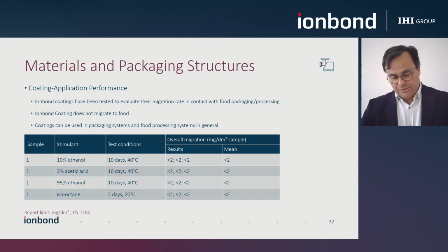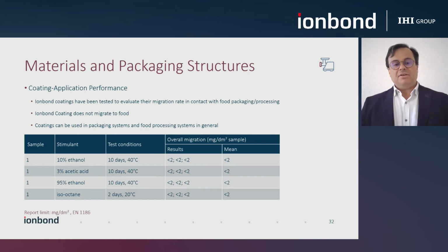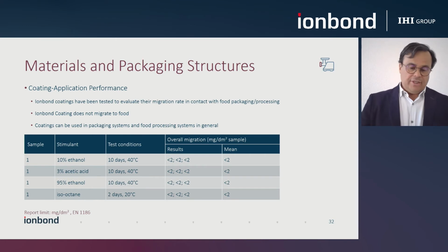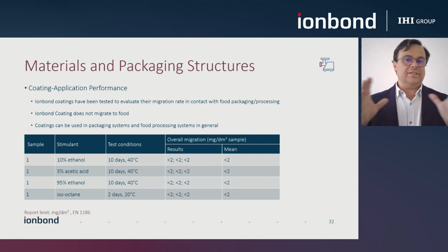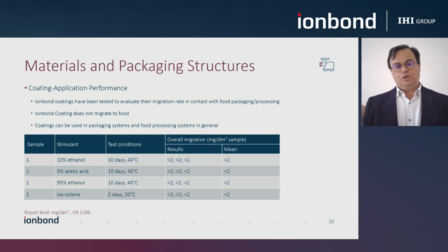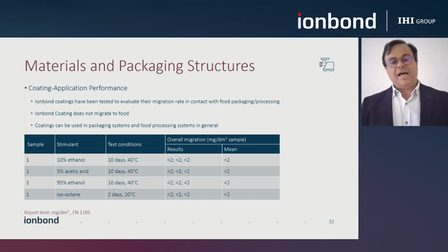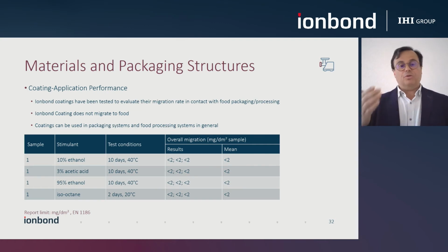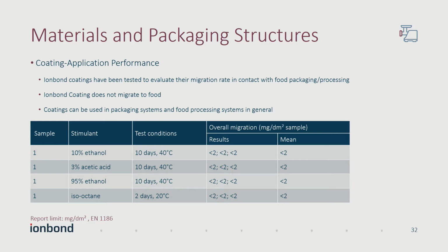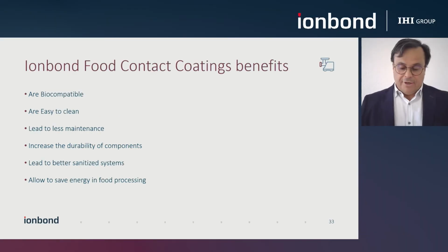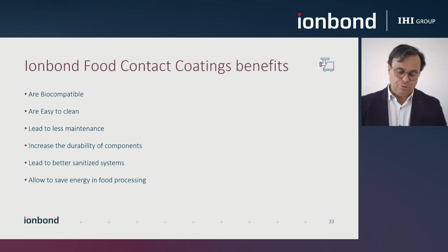But I also would like to add, as Jan has explained in his introduction, in the medical field, we have observed that not only the titanium nitride, but also the diamond-like carbon coatings are excellent ion barrier coatings. So by applying them on stainless steel surfaces, you really achieve an ion barrier, which is important from a migration concept. So I think it is important to remember that when you don't have a coating, it's much easier for you to have chemical migration or wear particles going into the food compared to the situation when you have a coating. And as you could see, the hard coating is lowering the wear and improving the overall performance of the system. So that is really the summary of the applications I wanted to guide you through.